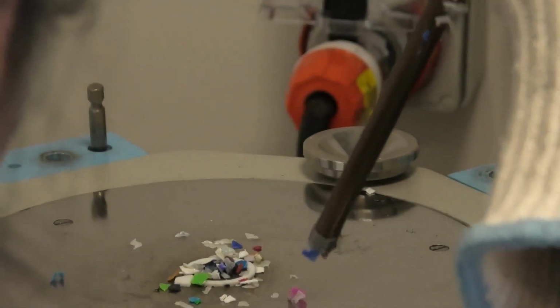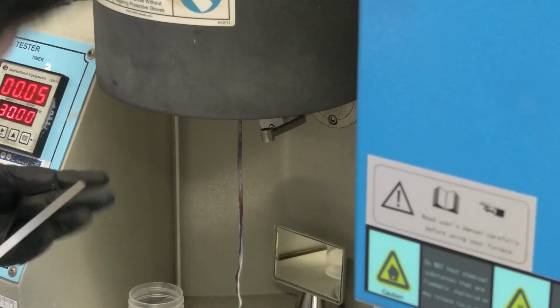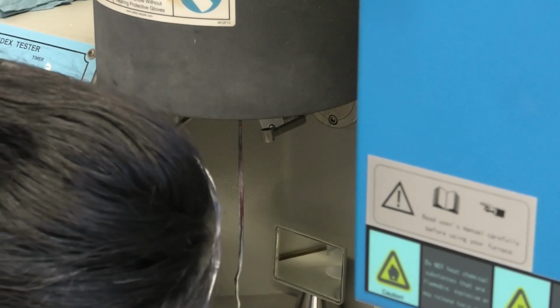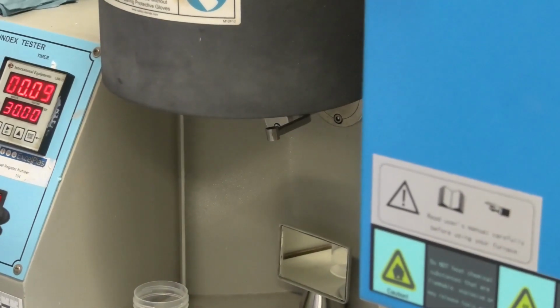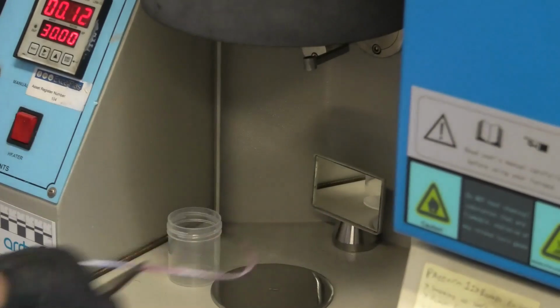So to conduct the test, we charge the barrel with a certain amount of polymer. We allow it to melt, and then once it's molten, we apply the load. And then the polymer melt will extrude through the orifice, and it'll come out looking like a little worm. And we then cut that worm off at a defined time interval. The load in this case is 2.16 kilograms.